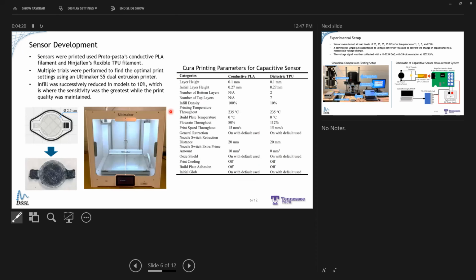First, for our sensor development, we used an Ultimaker S5 printer and went through an iterative process, and we found the parameters in this right table. The most important to pay attention to is the 10% infill. We used a lower infill percentage to help increase the sensitivity of our sensor, but found that anything lower than 10% actually reduced the quality of our sensor, so that's what we maintained it at.